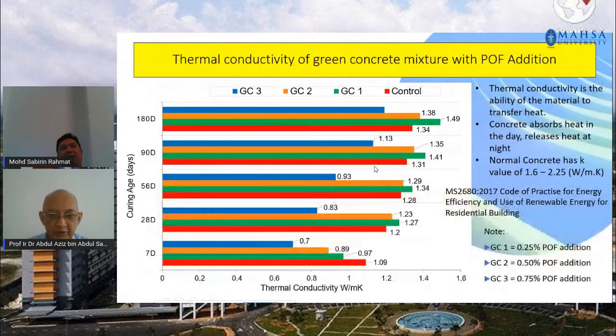And this is the result that we managed to obtain from the thermal conductivity of green concrete with palm oil fiber. So as you can see there, the normal concrete for the K value, K is the thermal conductivity value for the material, for normal concrete is about 1.6 to 2.25. And the one that we obtained for the green concrete is much less than that, the most is about 1.49, okay? Which is still less than 1.6. So this shows that the green concrete is a good insulator for heat.